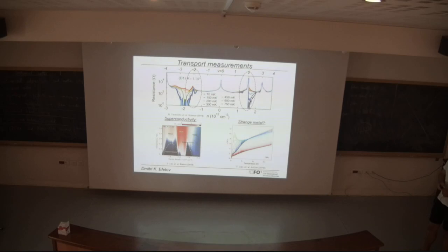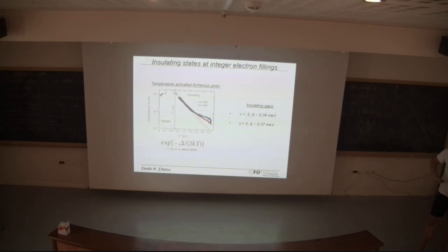Okay, so this brings me back to the transport measurements. Again, just to repeat, at this position here we have a band insulator, here we have a band insulator, here now we have 2 electrons per lattice site, and we also observe an insulator. And also here at exactly minus 2 electrons per lattice site, we also observe an insulator. And we are sure that these are gapped states because we can actually measure temperature activation at these. So we fix a Fermi energy at this state, and we measure the conductance as a function of inverse temperature. Because of any energy gap, this should give you some temperature activated behavior.